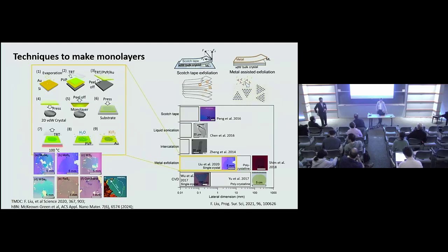Well, I don't think the stacking fault would be a huge challenge, but there's still a huge challenge to work with magnetic materials or CDW materials, as you have mentioned. The challenge actually comes from the chemistry. Here, we etch the gold with an aqueous solution that's a mixture of potassium iodide and iodine. This is actually mildly oxidative. And the fact that this is in a water environment with an oxidative environment unfortunately precludes applications to a bigger variety of materials.